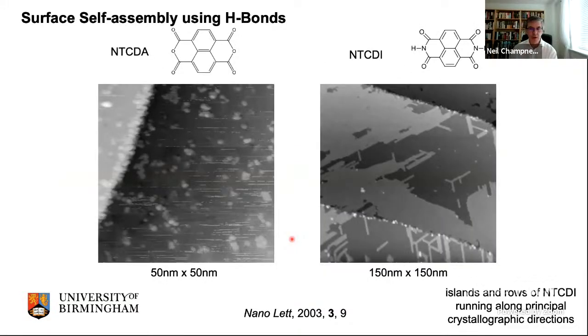Okay, so we then collaborated with some physicists, and in particular with Peter Beton, who still is a professor in Nottingham, and they're very good at scanning tunneling microscopy, so STM. If you deposit these onto a suitable surface, this is actually silver terminated silicon, you need a surface where the molecule will adsorb but is free to move around, and you need that motion for self-assembly to take place. If you look at the anhydride, where you don't expect any hydrogen bonds, you just get molecules moving all over the place, and it's very diffuse images, and there's no regular structure. If you look at the imide, you can see straight away that there is regular structure across the surface.